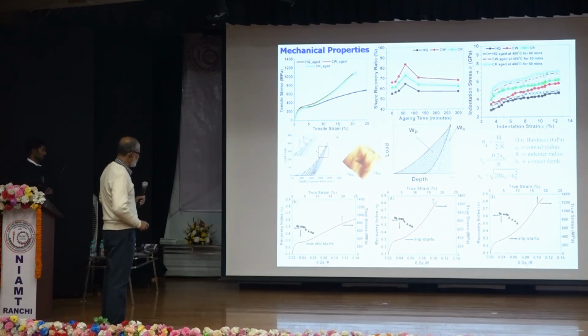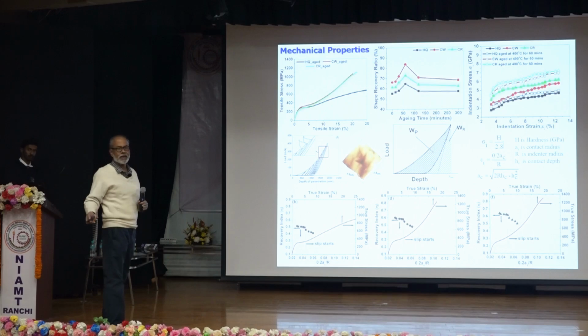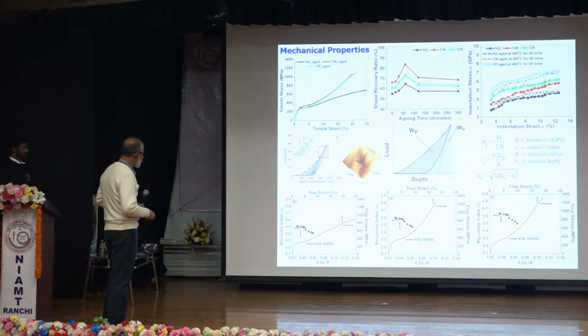And we plotted the variation of recovery index with strain given by the tower. We find there is a slope change. And this slope change uniquely coincides with the termination of recoverable strain and onset of plasticity in the macroscopic tensile experiment. So the nanoindentation experiment uniquely complies with the macroscopic tensile experiment in terms of recovery behavior, and it is on a single martensite plate. So that is how we could correlate this much.